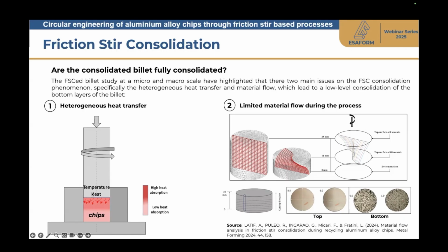Thank you very much. So the heat flux is just generated at the interface between the tool and the chips, just on one side, we will see. And it should be observed that in this way, we will have different temperature, but also different process conditions along the height of the billet, which will be consolidated. Furthermore, the process is characterized by a limited material flow during the process. This can be investigated both through numerical models and through experiments with some markers placed in the chips during the process. It should be observed that the material flow is limited, and this causes some limits in the process in terms of proper bonding.